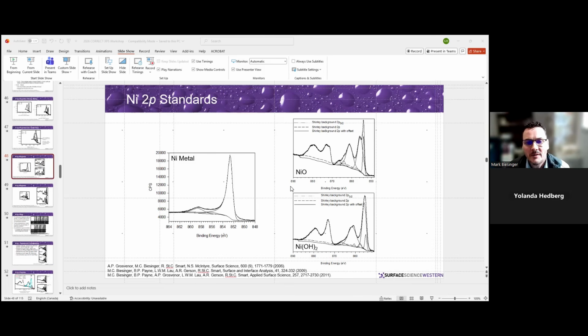Okay, instead of using a background offset, would it also be correct to use 2 Shirley backgrounds, one for the 3/2 region and one for the 1/2 region? Yes and no. It can work that way. The problem with nickel is the 2p 1/2 peaks of the metal overlap with the shake-up structure of the 2p 3/2 oxides spectrum. And so that kind of inflection point here isn't necessarily where the baseline is. There can be other stuff in there, and so you'd never quite get your baseline where it needs to be by using 2 baselines. That's why we use the offset.